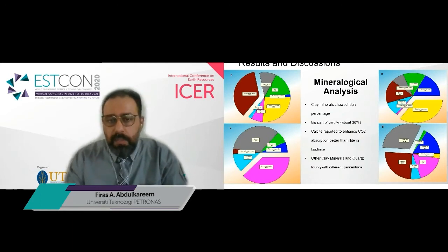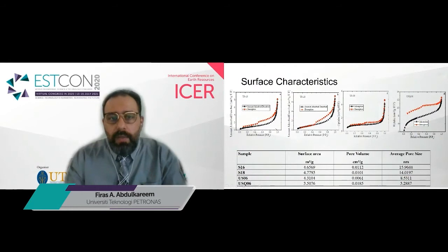rates, capacities, and selectivities. On the physical characteristics of the shell, we can see here that the nitrogen BET analysis shows some hysteresis in the absorption and desorption of the shell, which more or less refers to a delayed desorption process. That might refer to the shape of the shell pores and cavities, which more or less suggests open-ended pores and bottleneck type pores.